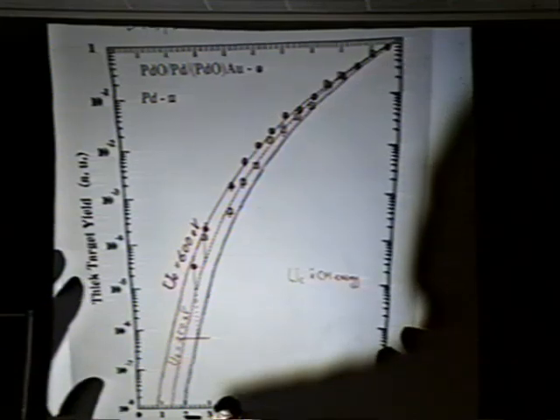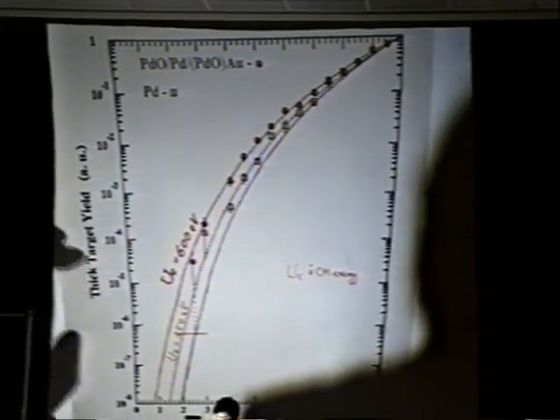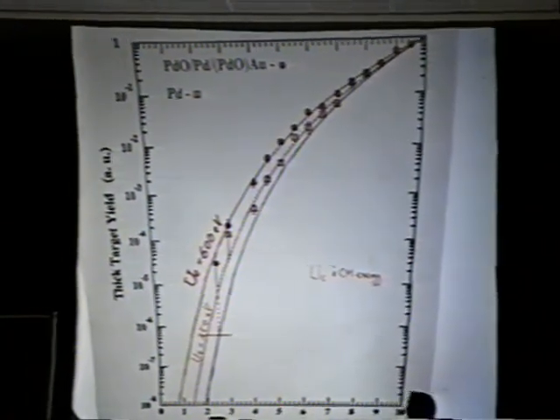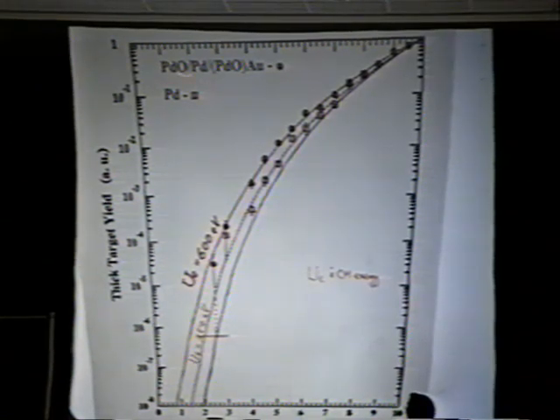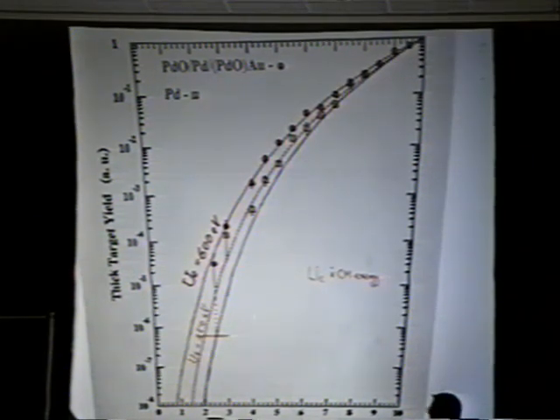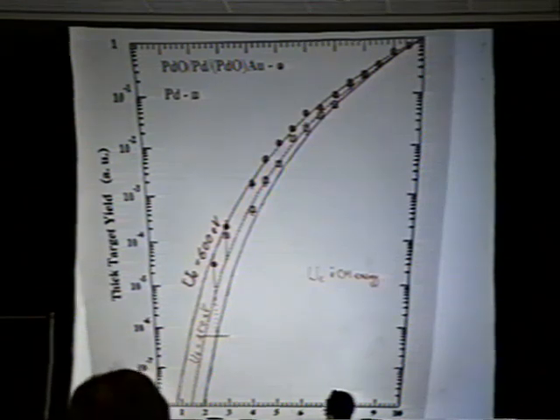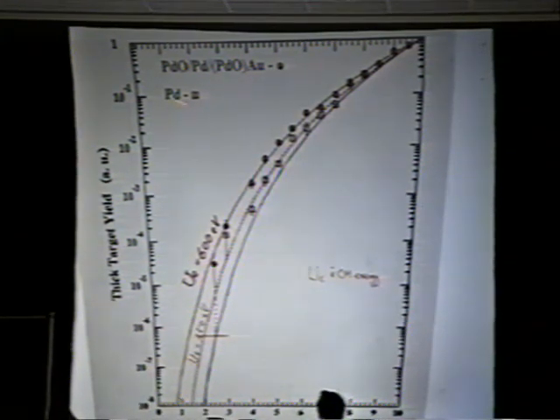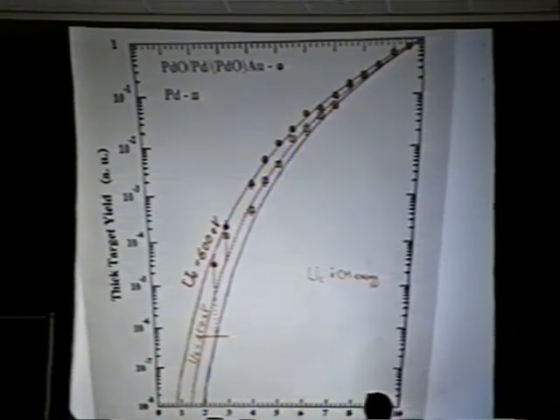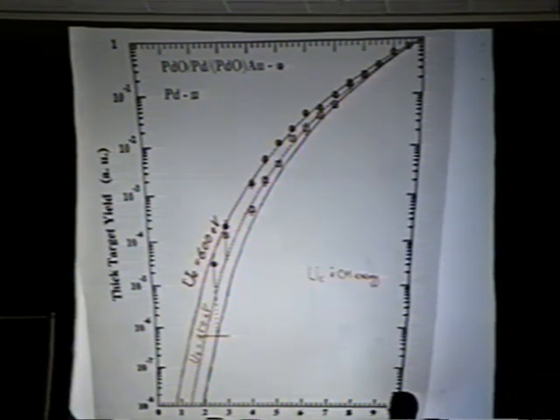We were very lucky to do the experiment with a Russian physicist. Here is in the audience Dr. Dixon. He brought us this kind of material, PdO, Pd, Au, gold. And you see, this is the same thick target yield for this target, and the red points are the result. The blue line is again the thick target yield without enhancement. And you see we also did a palladium measurement here, which I showed with an orange square box. So you can see the tremendous enhancement around here. This is about 50 times enhancement compared to without enhancement.